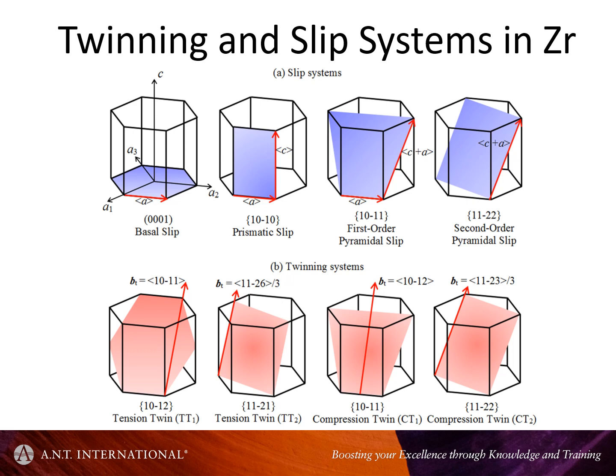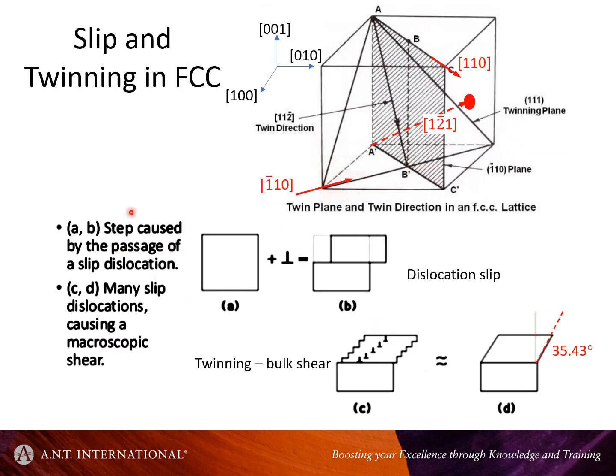Okay, so lots of possible options for twins in the hexagonal system. But in terms of channeling, a lot of the ambiguity comes up when you have twins in the FCC system, face-centered cubic system, austenitic alloys. So there's only one twin to consider, and that's one that shares a common plane with the normal slip direction, the dislocation slip, the a/2 110 slip.